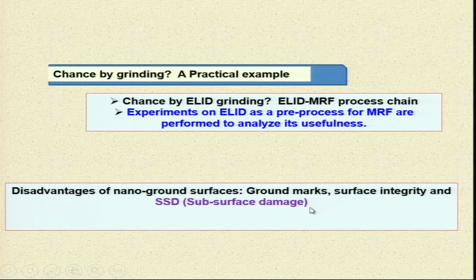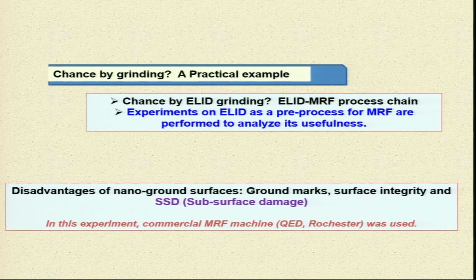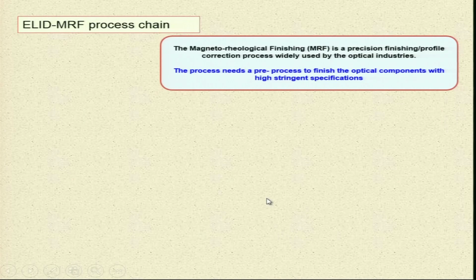Disadvantages of nano ground surfaces: you can find ground marks over there, surface integrity issues and subsurface damage. These are some of the problems that you find in case of micro grinding. In this experiment, a commercial MRF machine that was built first time by QED Rochester, USA was used for performing the experiments. ELID-MRF process chain: magneto-rheological finishing is a precision finishing profile correction process widely used by the optical